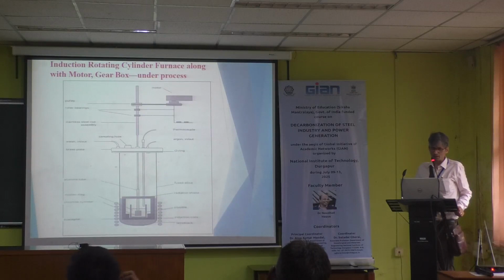And this is the rotating cylinder furnace. Here there is a 1 kg crucible which can hold half to 1 kg of slag or ferroalloy, anything that can be melted up to 1600 degrees centigrade. And this is the rotating cylinder, so that at its tip one can fit any object which you want to study from a dissolution point of view in this liquid pool.